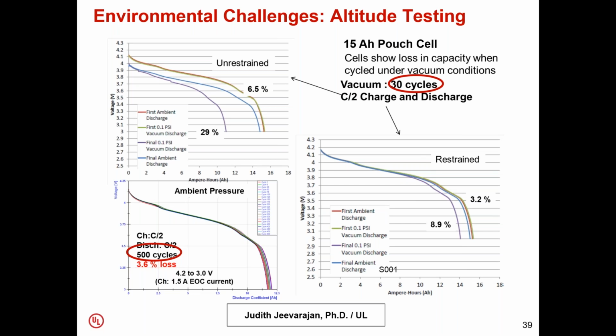But what I wanted to show is that when you have a pouch design cell, you have to have restraints on the pouch. And if you look at the example that I've given here, at ambient pressures, we found that after 500 cycles, we lost less than 4% of the capacity. But when we cycled it in a vacuum environment, within 30 cycles, we actually lost 8.9% of the capacity in a restrained mode and 29% of the capacity in unrestrained mode.